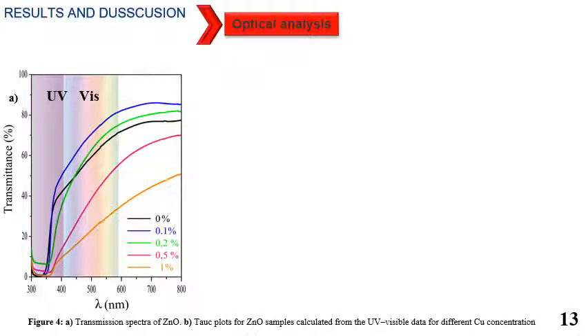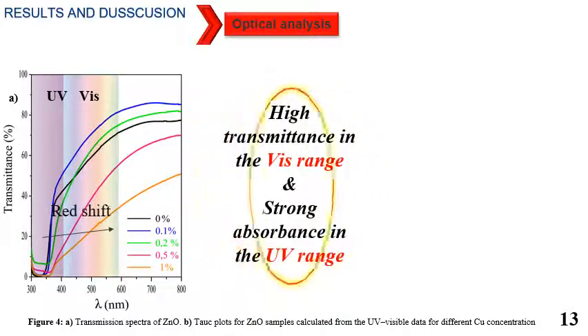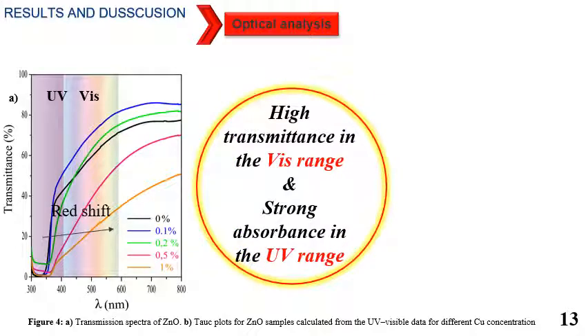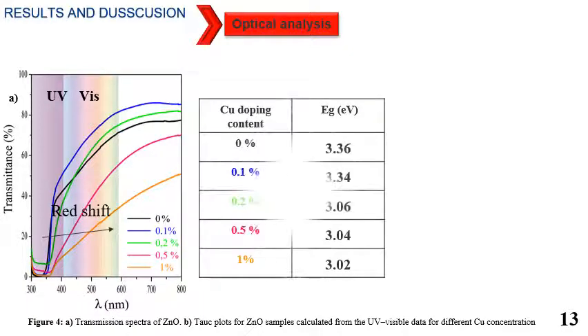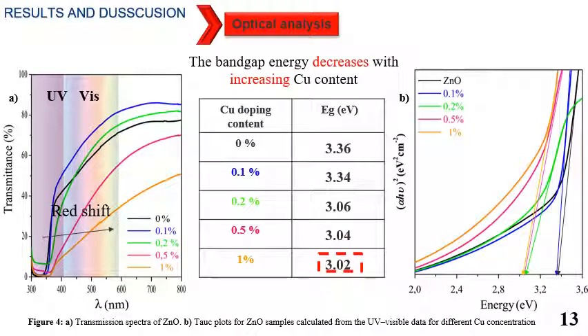The influence of copper doping on the transmission and the band gap of the zinc oxide samples was studied by UV-visible spectrophotometry. It is clear that doped zinc oxide exhibits a gradual shift toward the longer wavelength side compared to pure zinc oxide. The transmission value increases to a maximum value of 86% for samples doped with 0.1%. The highest transmission value obtained for doped samples can therefore be considered a preferable material for thin film solar cell applications, as they require the use of materials with high optical transparency. The band gap energy estimated from the Tauc plot shows that when the copper content increases, the band gap value decreases from 3.36 to 3.02 electron volts.